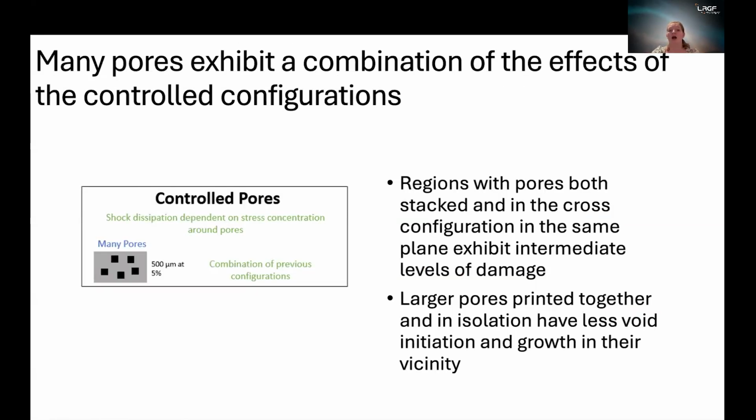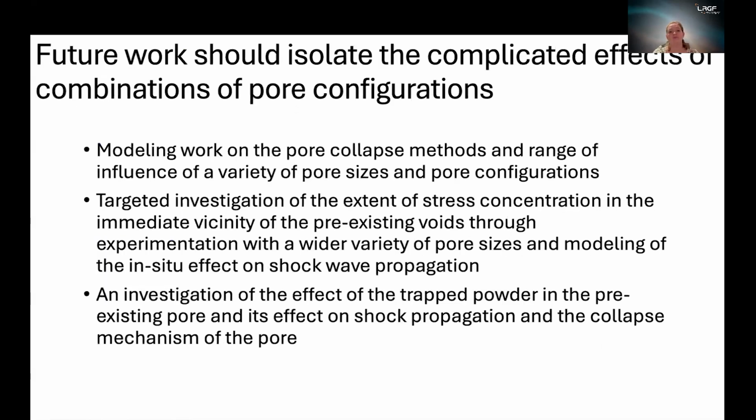So we do see a combination of the effects from the single, cross, and stacked configurations in this less controlled random porosity sample. So regions with both stacked and the cross configurations in the same plane exhibit some intermediate levels of damage, whereas larger pores printed together and in isolation have less void initiation and growth in their vicinity. So we see the continuation of the trends that we identified and isolated with the controlled configuration growing into the many pores in the random configuration.